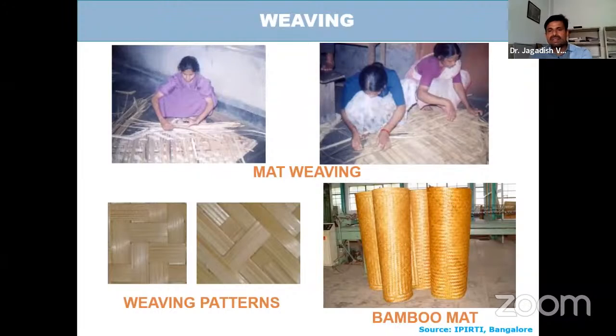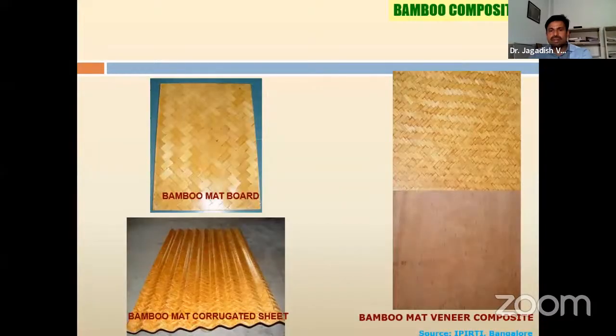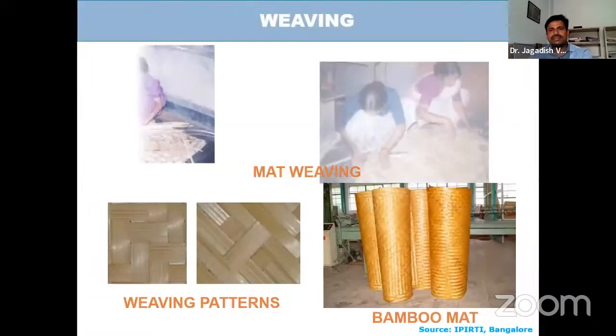After dipping the mats into resin, they take them out and dry them. And then you place a number of these mats into a hot press, and apply temperature and pressure. If the die of the hot press is flat, you get a flat board, and if the die of the hot press is corrugated in shape, you get bamboo mat corrugated sheets.